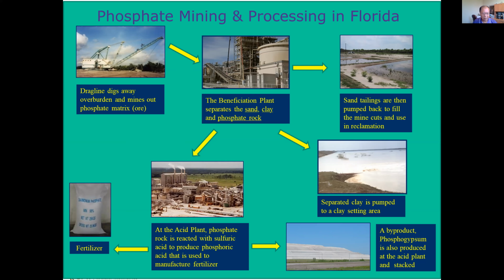Phosphate mining in Florida is all surface mining using dragline. The phosphate ore consists of roughly 1/3 each of clay, phosphate rock, and sand. So the beneficiation process involves washing the clay first, desliming, followed by sizing. After sizing, the materials go through a flotation process to remove the silica or sand. In that process, it produces a flotation concentrate and also a pebble product, which does not need flotation. The pebble product accounts for maybe 20 to 30% of the product. The flotation concentrate accounts for 70%.